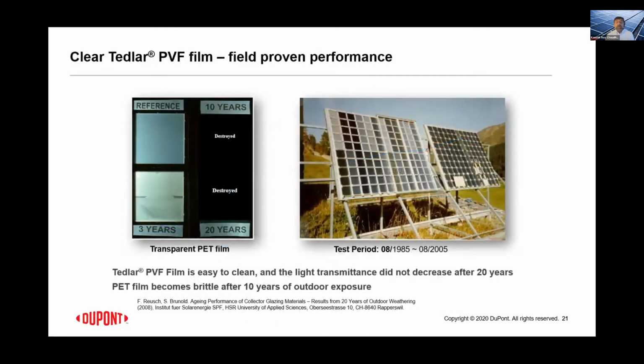There has been some field-based work. This is again with the older generation of the transparent Tedlar film, which translates very well to the newer generation, which is in fact, if anything, a much improved version. So this study was actually not done by us. This was an external institute. It was done in Switzerland, and transparent PET-based films were compared with transparent Tedlar-based films. And what was seen was that the light transmittance in the Tedlar film didn't decrease even after 20 years. However, the PET-based film became brittle just after 10 years of outdoor exposure. So we are always trying to make this connection between indoor accelerated testing and outdoor exposure. So this is a good touch point on that one.